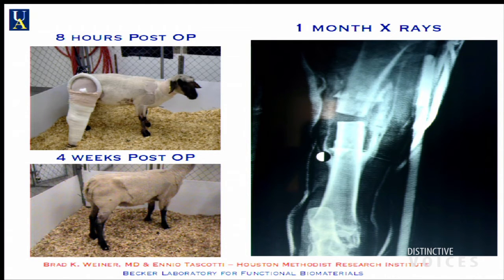When you take the x-ray, and then you take it again, and you take it again, why isn't there bone in the middle? There's bone here. You can see that the scaffold's invisible, but there's bone growing around the entire outside, 360 degrees around, because that's the fat knuckle hypothesis I talked about before, and the blood supply doesn't come from the middle, it comes from the membrane. And so the shell rubbing on the membrane produced enough osteogenic signal to get bone to grow actually around the tube rather than through the tube. Okay? It took a while to figure that out.